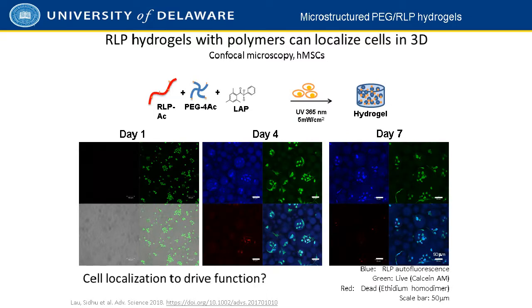And we've shown this in related work where we incubate RLPs that are photo cross-linkable. In this case, they're also combined with polyethylene glycol, so a PEG acrylate. That's for different reasons, but they're photo cross-linked. The microstructured hydrogel still forms. And what you can see is the blue is the autofluorescence of the RLP domain. So you can see that they're regularly distributed throughout the matrix. They're very, very cell-friendly. So the green images are the calcein dye that stains live cells. We also have in here a red dye, ethidium homodimer, that will stain the dead cells red. And you can see that there are no red cells really to be seen in these materials. And then the merged image on the bottom right of each panel shows that the cells are isolated in the regions where there are RLPs.